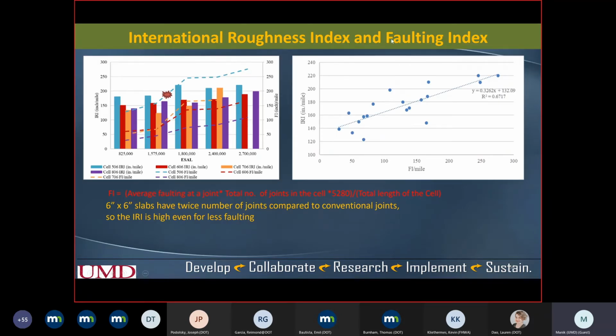We also looked at the International Roughness Index, and we also coined a factor called faulting index. Faulting index basically takes care of the faulting for all the joints, and if you convert it into per mile, the unit, inch per mile, is the same as the unit for the IRI. So these lines are the faulting index, and these bars here are the IRI. The IRI values for the plain concrete were high from the very beginning. You can see the blue line here. When we looked at the IRI value, we found that at 1.7 million ESALs the IRI exceeded the critical value, 173 inches per mile, and at that time faulting was 0.1 inch.